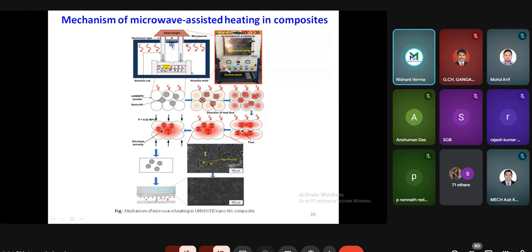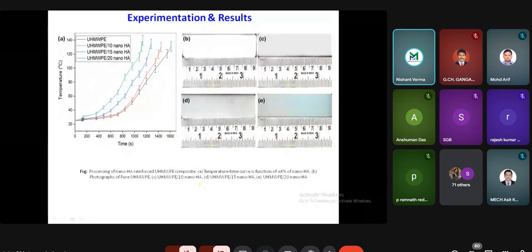In this figure from the SEM, you can see the higher porosity without the effect of pressure. But after applying the pressure of 2 megapascal, we have attained a dense polymer, and we can see the scanning electron micrograph of this material. These are the temperature time curves for the neat high molecular weight polyethylene and 10% nanohydroxyapatite, 15% nanohydroxyapatite, and 20% nanohydroxyapatite. So we can see the temperature time curve for this material, this material, and this material. We can see that the same temperature is reached in 1600 seconds in the case of neat ultra high molecular weight polyethylene,